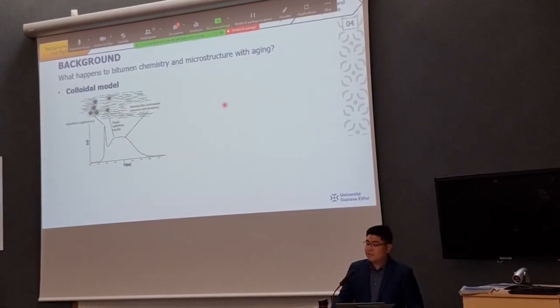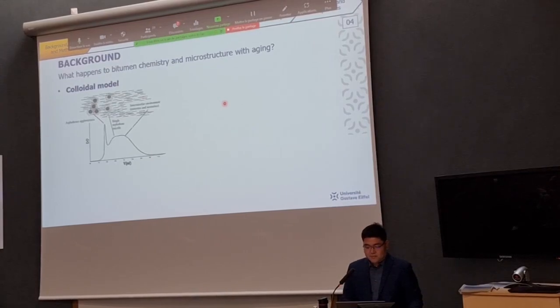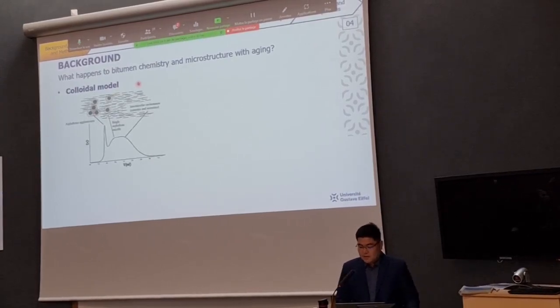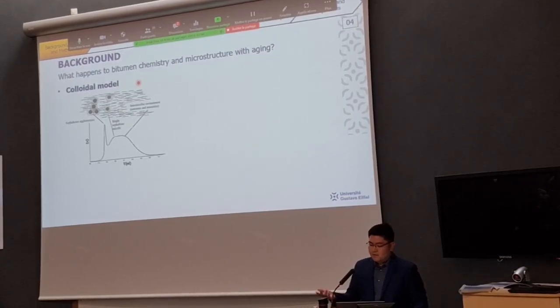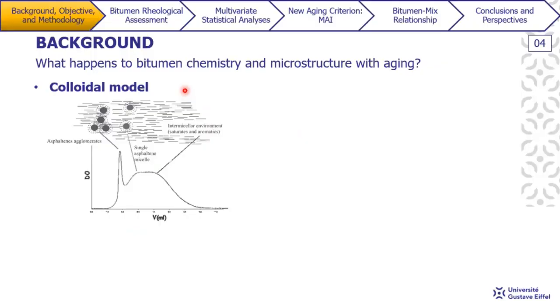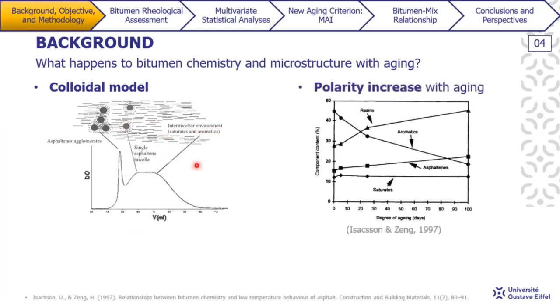But what happens to bitumen chemistry and microstructure with aging? So among the several models found in the literature, the colloidal model seems to remain the most accepted model to describe bitumen structure, even though there are still some aspects to be understood. According to this model, bitumen can be seen as a colloidal system consisting of high molecular weight asphaltene micelles that are dispersed in an intermicellar environment with lower molecular weight. From a chemical point of view, bitumen has traditionally been fractionated into four generic groups, named SARA, which is an acronym for saturates, aromatics, resins, and asphaltenes.